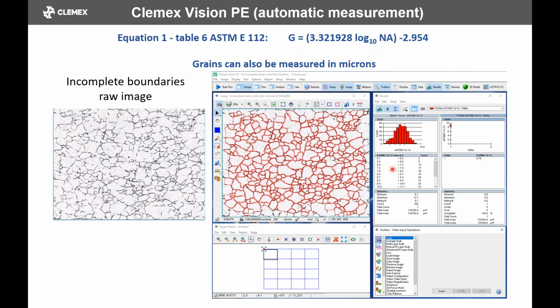When you're scanning, you can see your grain size vary. What we also have is the field measurement, which is certainly very interesting, because you end up measuring by the intercept method. All the camera lines that you have will intercept a detected line and count the segment. It will measure horizontally and vertically to end up with something that is quite accurate. You can see the measurements are similar, 8.7 and 8.8. We have similar values, even though it's counted differently.